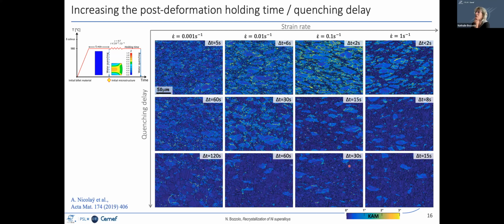So here you see that with a strain rate of 0.1 per second, which is still a reasonable value. I mean, it's not particularly fast deformation. It's typical for a hydraulic press forging, for example. You see that after deformation to a macroscopic strain level of 0.7, you end up with quite a low value or low fraction for dynamic recrystallization, but post-dynamic recrystallization completes recrystallization in less than a minute. So if you compare these typical times with the cooling times required at the industrial scale, you definitely need to consider both dynamic kinetics, dynamic recrystallization kinetics, and what happens after deformation.